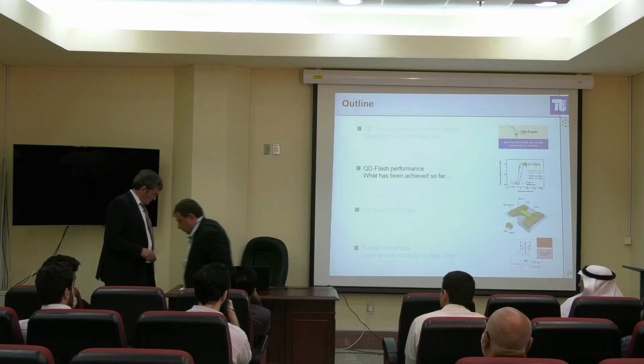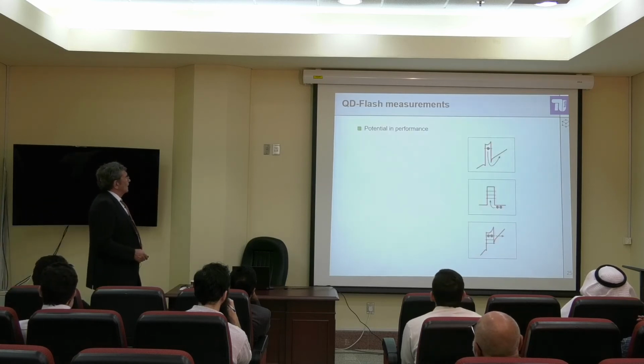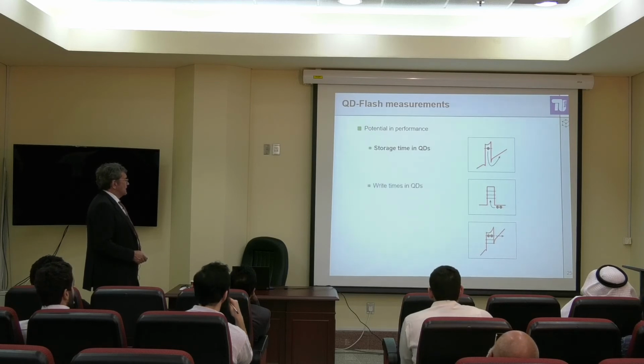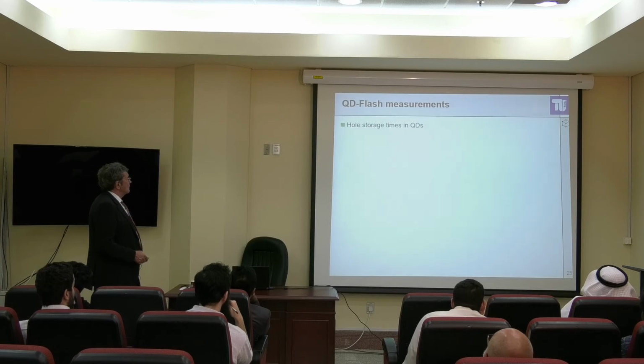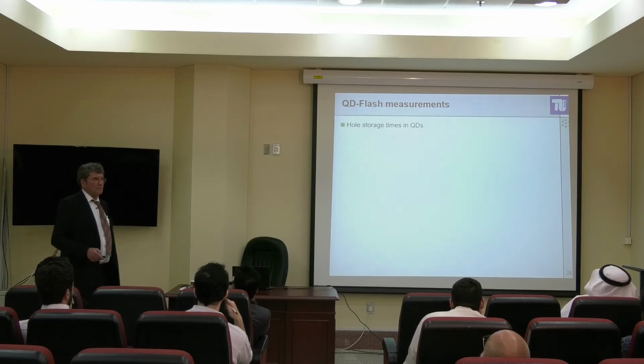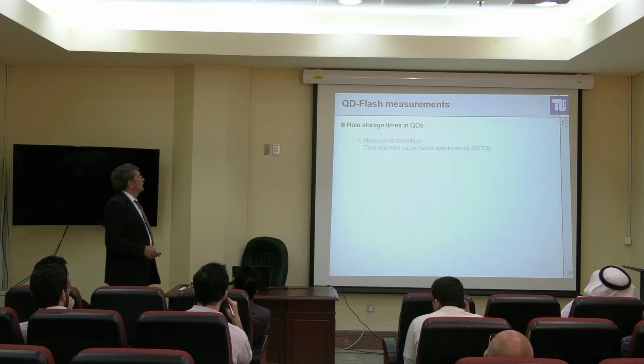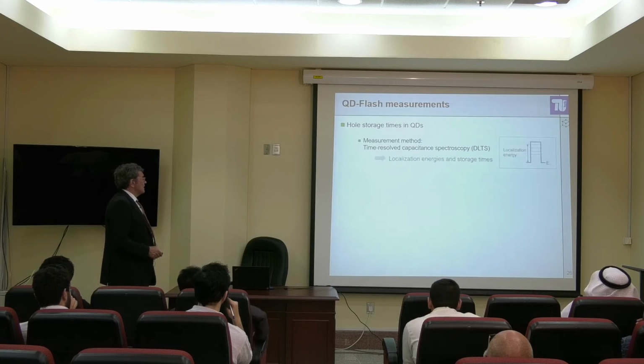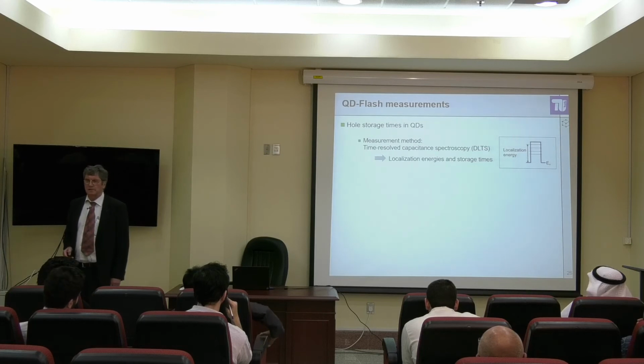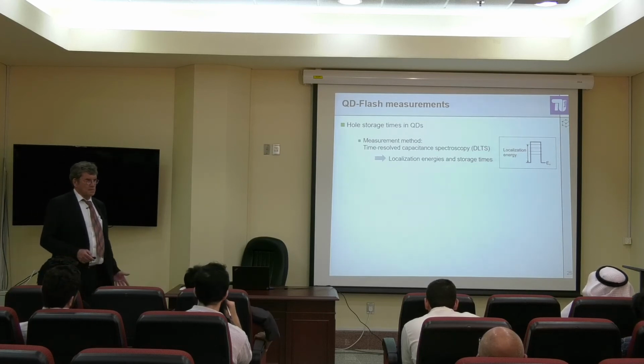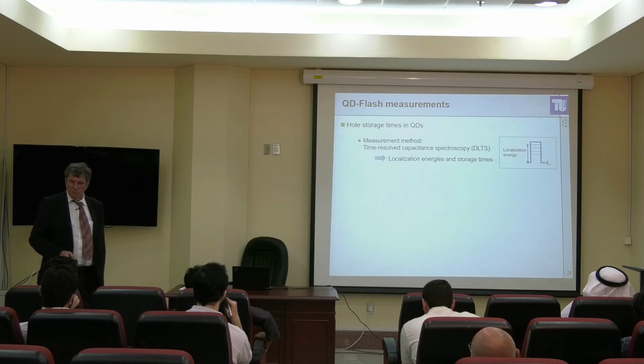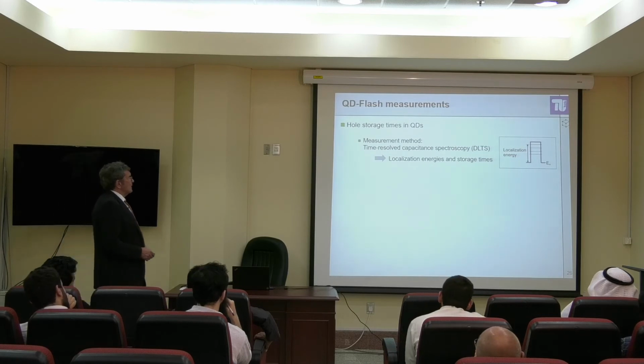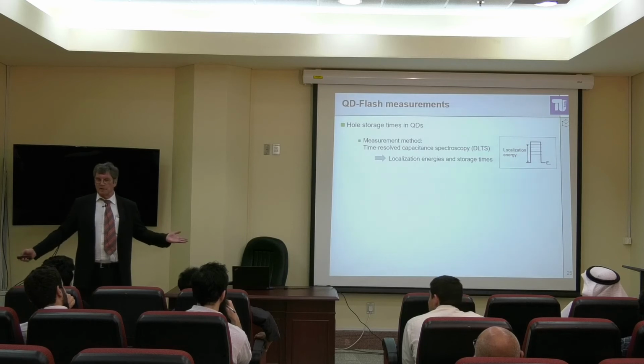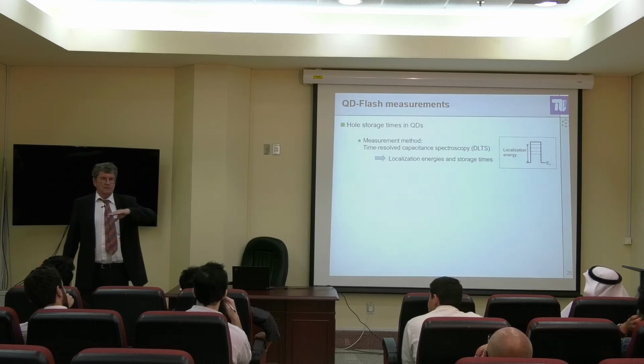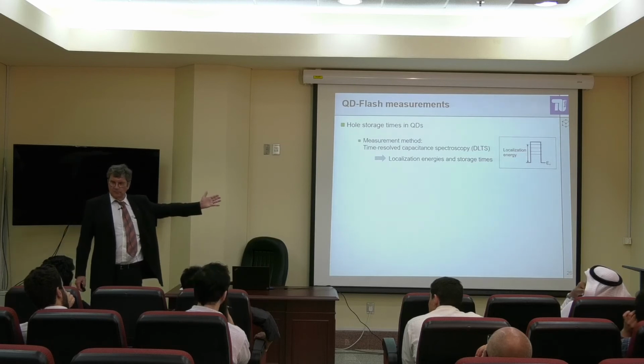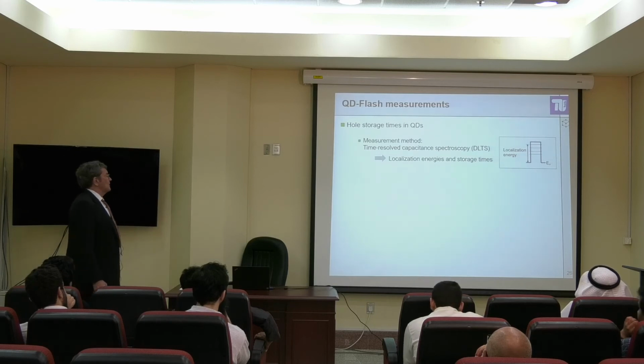So what has been done so far? Storage time, number one. Write times, erase times. I will focus a little on the storage time, and the rest I will run through. We use a measurement method called capacitance spectroscopy. That is an electrical engineering method where you measure the capacitance, C, as a function of voltage. And there is a variation of that where you do it time resolved, like time resolved luminescence. You excite a sample, you look at the decay of light; you can look at the decay of capacitance. It's much closer to electrical engineering than luminescence.